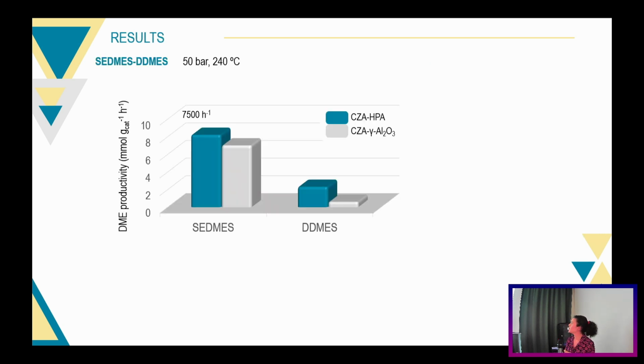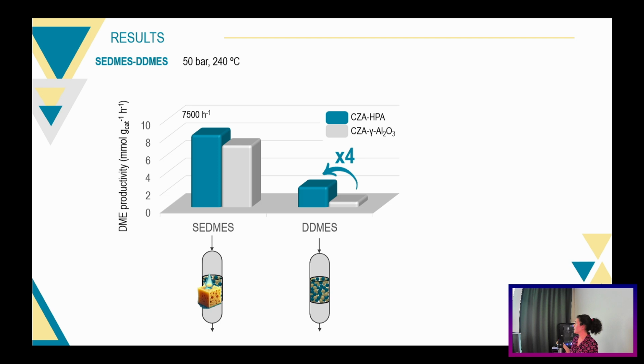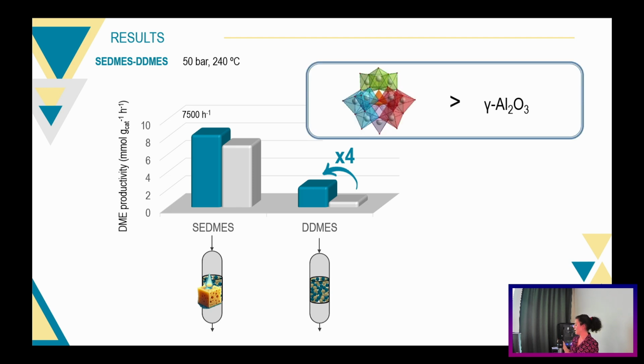So moving ahead to the results section, I show you here the DME productivity for both processes and both catalytic beds. Let's look first at the direct DME synthesis, meaning without water sorption. From these results, we can see that the heteropolyacid containing bed was much more active than the gamma alumina containing bed. This observation was also made at other operating conditions.